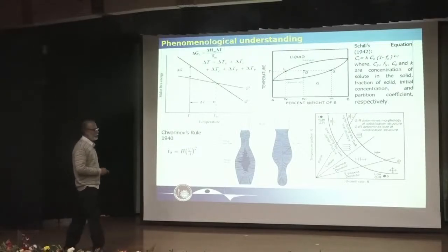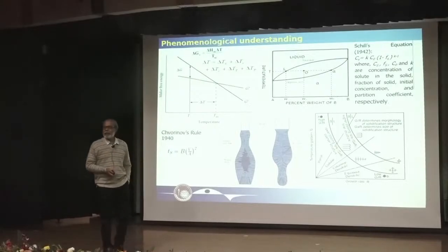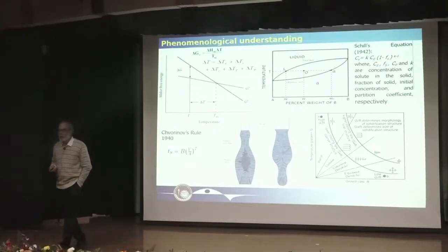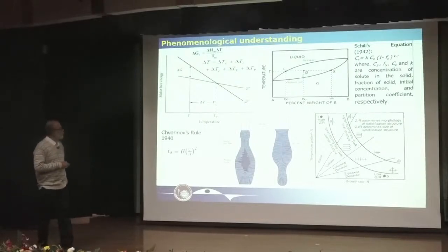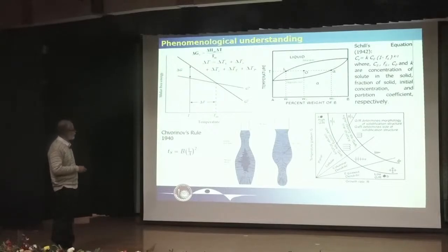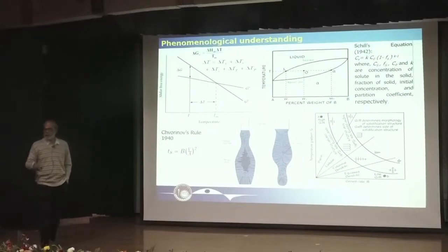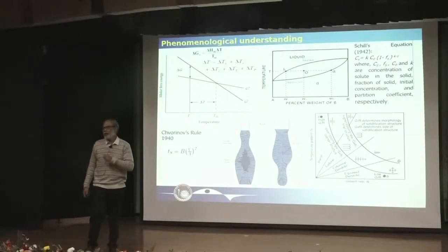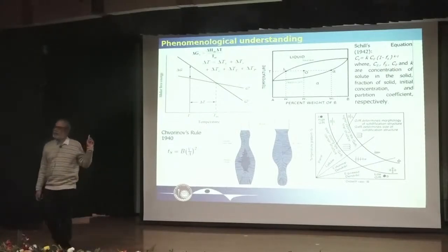Similarly, people used Gibbs' theory for development of phase diagrams in a wide range of alloys. But this phase diagram was basically an equilibrium diagram. For example, when solidification proceeds at an average composition, the common metallurgical concept is that we determine the fraction of solid as this length, this opposite arm, it is the composition of solid, this is the composition of liquid, so this arm divided by this arm. So that we call the lever rule. This is an equilibrium concept. But it doesn't work in the solidification process. During this period, people were trying to go for computational development of phase diagrams. But this equilibrium concept was not working.